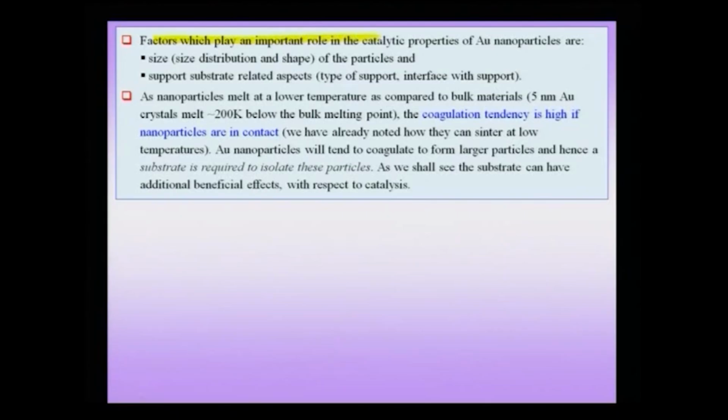Factors which play an important role in catalytic properties of gold are, first of course, when you are talking about gold nanoparticles, size, that means size and size distribution and shape of the gold nanoparticle, and additionally, which is the important point, is the substrate. That means, what is the type of the support, what is the interface with the support substrate, all these play an important role in the final outcome of the gold nanoparticles'